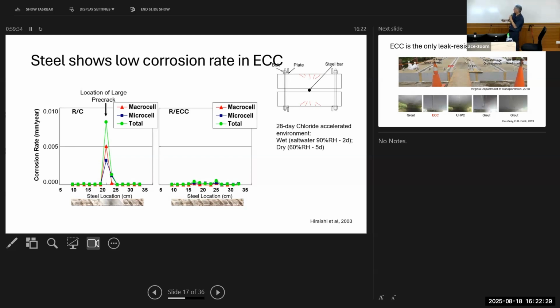Now, for the reinforced concrete beam, there is only one crack, and after they pulled open the specimen and looked at the rebar there, they saw a large amount of corrosion debris on that rebar, and the measured corrosion rate is very, very high. Okay, just at one spot, but very, very high. In the case of the ECC beam, they see corrosion spread over a length of the rebar, and that's because you have multiple micro cracks, but the corrosion rate is very, very low. Okay, so this is another confirmation that we can expect high durability of infrastructure when we use ECC that has intrinsically very tight crack width.